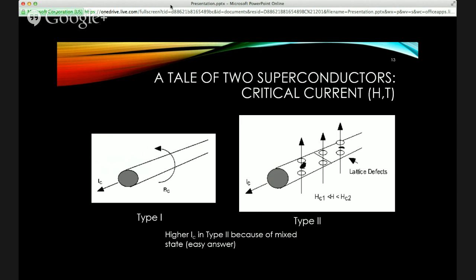So you can see it better here. That's the type one again, where, using your right-hand rule, you have the current flowing out of the superconductor, and the magnetic field encircles it. With the type two superconductor, where you have the current flowing out of it, you have that magnetic field flowing through these flux lines. Imagine these circles are those red circles that we saw previously. And then you have a shielding current encircling each of those lines. And so you have a higher critical current in type two, and that's directly related to that mixed state.